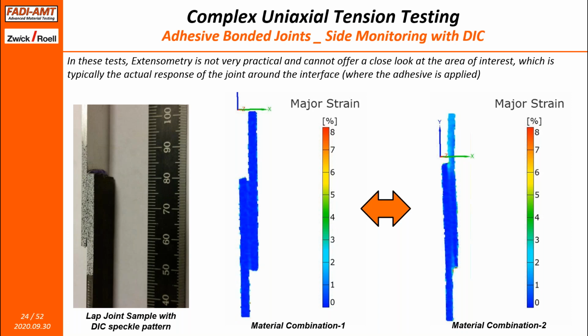And typically, you basically pull this on a standard tension machine and you report the load displacement. In this particular case, we use the DIC in a special case, in a side monitoring mode, and you can see how we are able to monitor that very thin layer of adhesive during the test, which is at the interface between the two sheet metals. And in this case, we show how the DIC is able to define or identify the differences between certain combinations of materials in adhesive bonded joints. On the left, there's a combination different than the right.